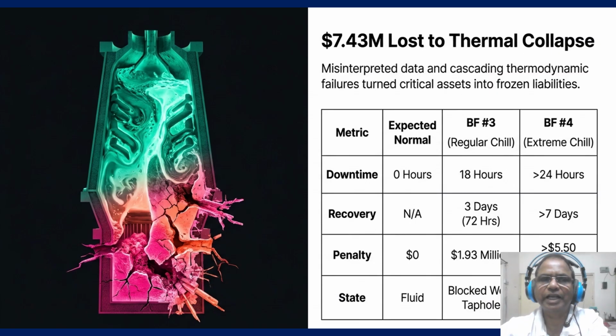On the left, our expected normal shows zero downtime and a fluid state. Now look at BF number 4 on the far side. That was not just a regular chill. This was an extreme event resulting in over 24 hours of downtime and more than 7 days of recovery time. The penalty alone exceeds $5.57 million. Notice the state now: total loss of taphole.